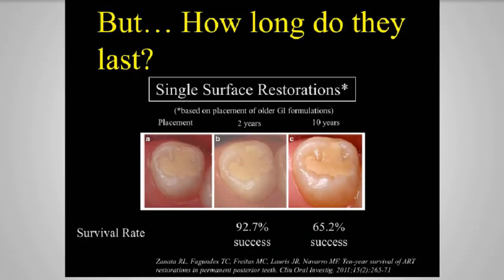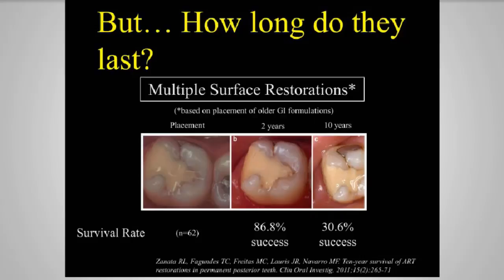And it's interesting, there have been some studies done, and this again was done on older formulations, because to have 10-year data, this is before they came out with some of the new improved higher filler particle materials. But what they found was single surface restorations had a 65% success rate at 10 years. So 2 out of 3 were still there at 10 years. That's not bad. What about multiple surface? Well, they don't last as long with those, but they still enjoyed a 30% success rate at 10 years. The way these tend to break is bulk fracture in these larger restorations where you have interproximal.